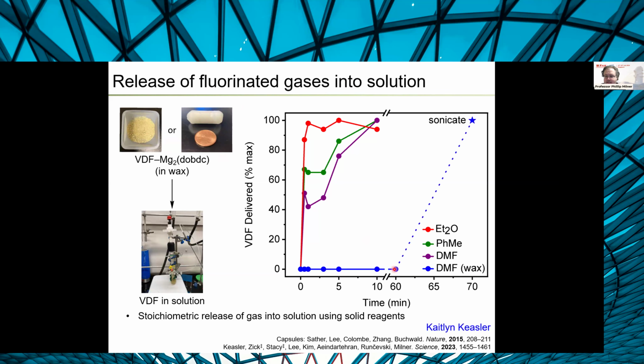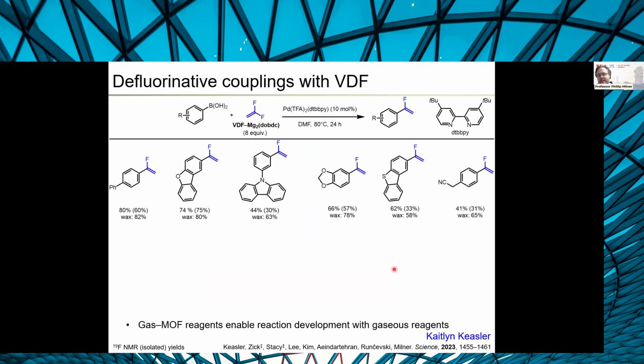So I'll take you through now in the last portion of my talk some of the reactions we have found using these gas-loaded MOFs. We were really interested in using vinylidene fluoride as a universal kind of building block to make any kind of fluorinated alkene that we could. And what we found very quickly is that this gas is surprisingly electrophilic and engages in defluorinative couplings quite easily here, where we can actually see that with using a simple palladium catalyst here, we can actually couple vinylidene fluoride with boronic acids to make these alpha fluorostyrene analogs.